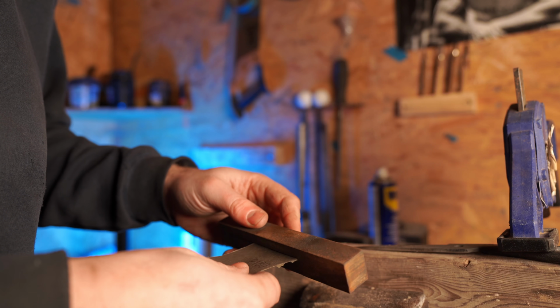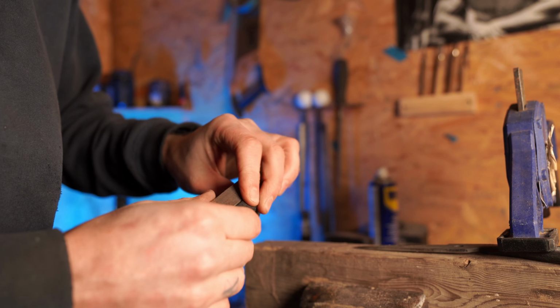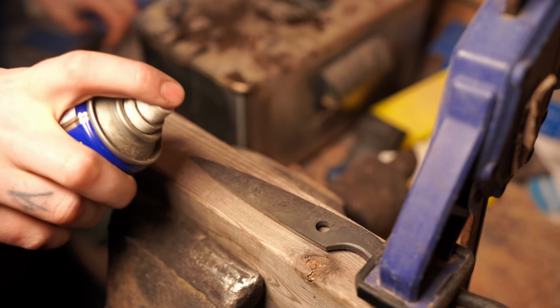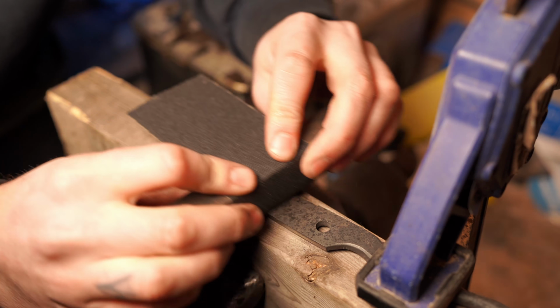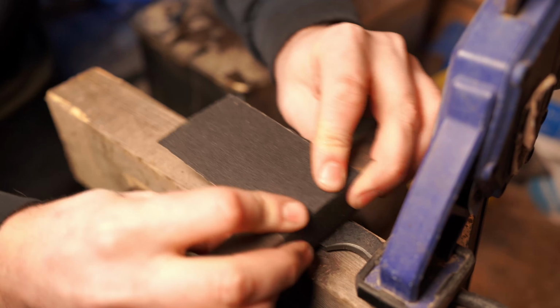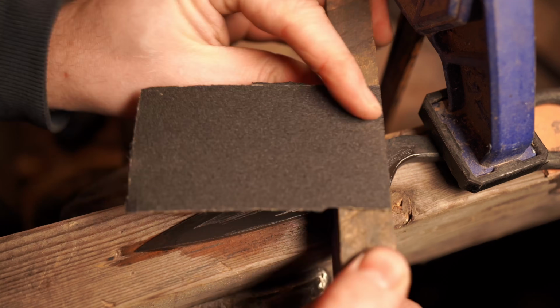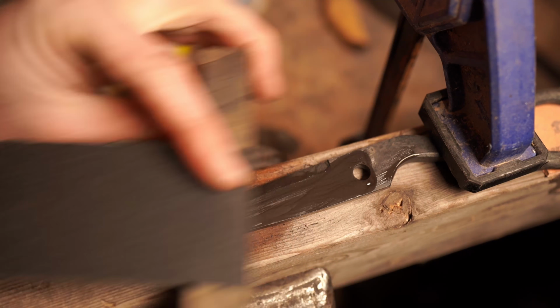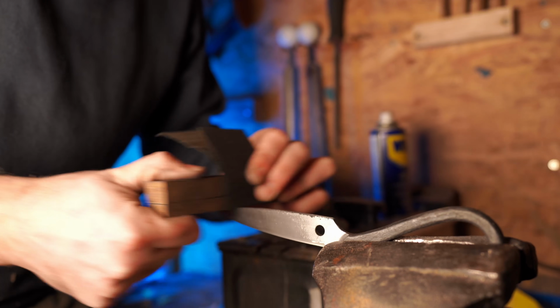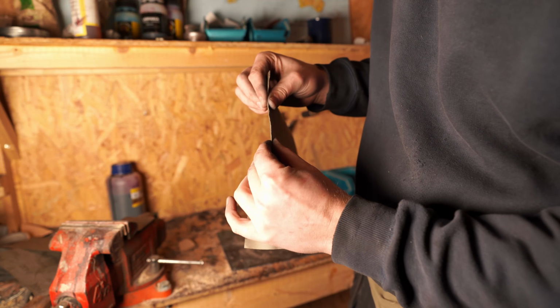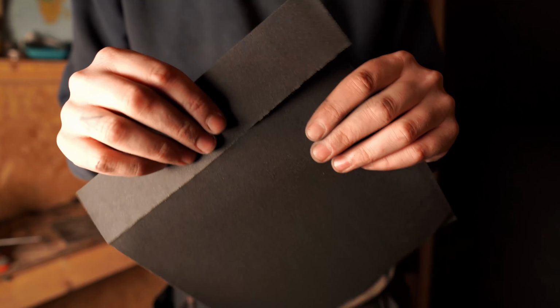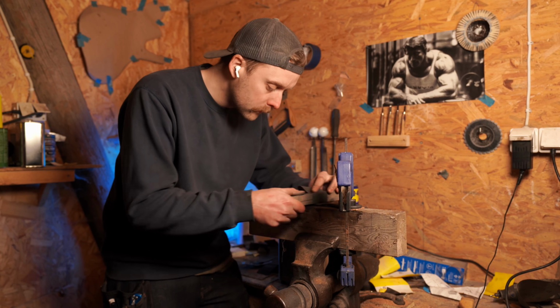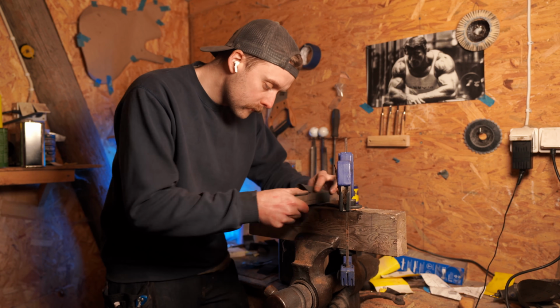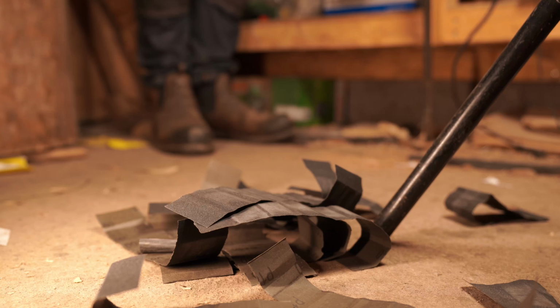It's time for hand sanding. Now this is a long and very repetitive process. I start out with a 180 grit sandpaper and the idea is to sand it until it looks good everywhere. I then switch to a 240 grit sandpaper and keep going until all the 180 grit scratches are gone. After that I move on to 320 and so on until I'm happy with it. How far you take this is really up to you. Personally, I stop at a sloppy 800 grit, but if you want to go further, you most definitely can.